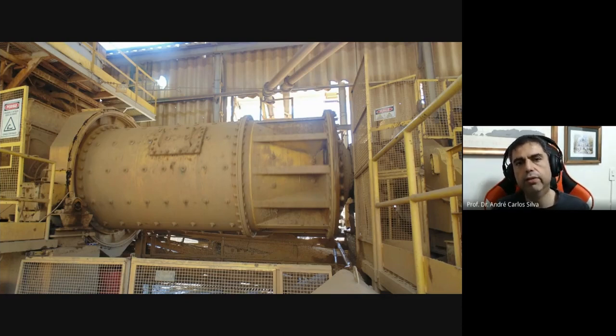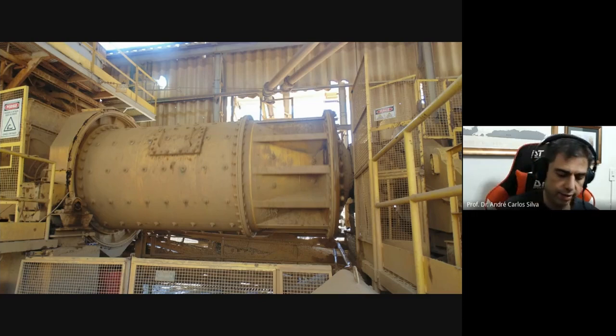And that's why you're going to remain with bigger particles, and a bar mill, on the other hand, can do the trick, okay? So this is another shot coming from Catalan. This is our bar mill. And these items that you can see over here, those are bolts, okay, nuts and bolts. It's because inside of the mill, we also have liners. And those liners were designed to prevent any kind of damage to your mill body.